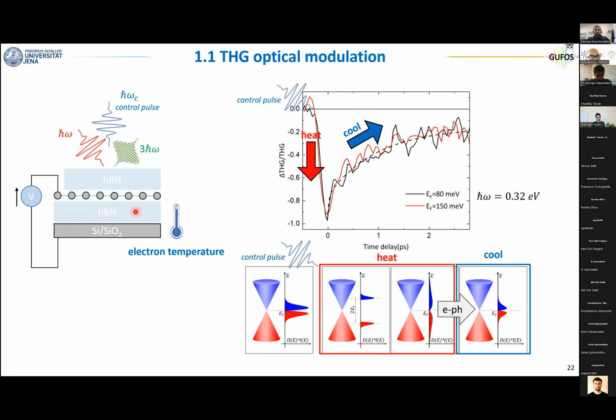Now the idea is the following. We use the gate voltage to fix the Fermi energy, and then we arrive with the control pulse. And now I plot here on the y-axis how much I'm changing the third harmonic. This graph is normalized because I only want to focus on the dynamics. And on the x-axis, I have the time scale, so the delay between the control pulse and the fundamental beam. So time 0 means the control pulse arrives together with the fundamental beam. Here you see there is a very rapid drop in the third harmonic efficiency, and then a certain recombination dynamics that takes something in the range of picoseconds.